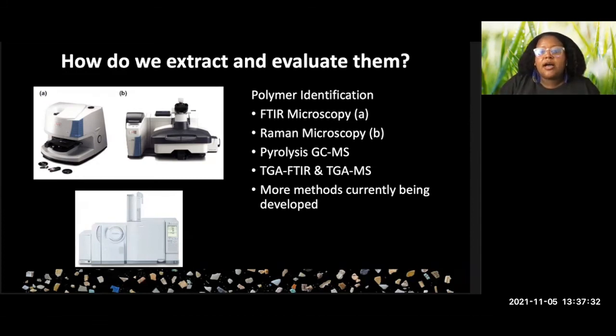Additionally, a lot of the polymer ID databases are for pristine materials. So with FTIR and Raman, you get a spectra. And what you typically do is you try and match the spectra based on spectral libraries that have been established by different labs, material scientists, among other entities, right? However, one thing to note about these spectral libraries is that they are for pristine materials, not materials out there in the environment. So confirming polymer ID can be very difficult, and that is why we need open source software or spectral libraries of environmental microplastics. What we mean by that is microplastics that have been out there in the environment for a while, that have been isolated from studies.